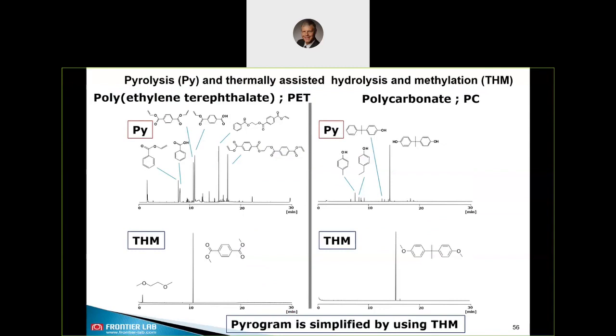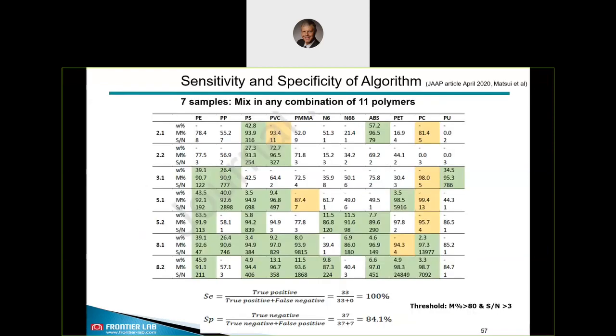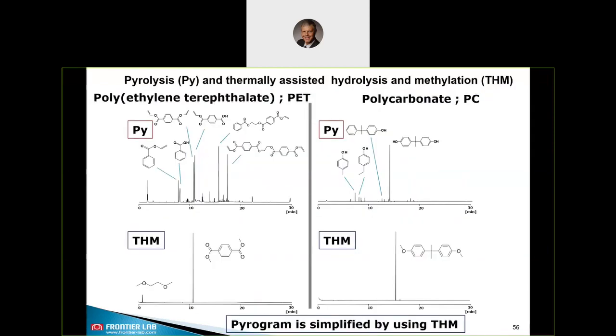Since PET and polycarbonate were already discussed, TMAH can be used as a derivatization agent for microplastic detection, as also reported by Scholtz-Bertja et al. Two nice effects of TMAH derivatization are that the resulting chromatogram is simplified and basically only one major peak product can be seen, ensuring high sensitivity for PET and polycarbonate. This derivatization also improves sensitivity for polyurethane for the same reasons.